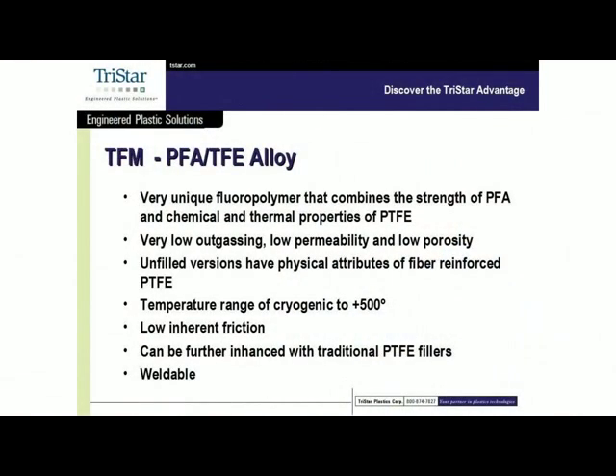This is a product that comes from Dyneon. They are the sole source for TFM. And it comes in a couple of different versions, but it's easily processed. It can be compression molded. It can be extruded. There are other additives that can be put into it to strengthen it, but TFM by itself has pretty good strength because of that PFA factor. Some of the other things about TFM, it has very low outgassing. Again, a big thing if you're in vacuum.